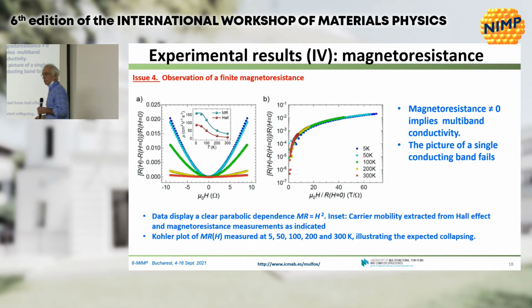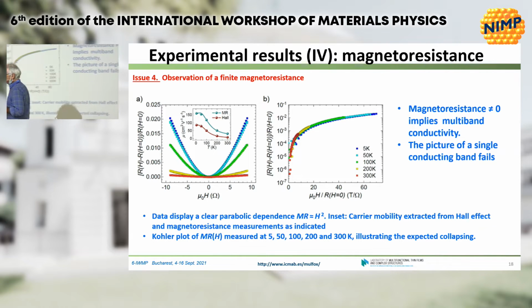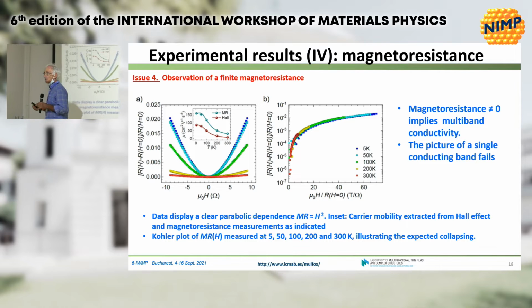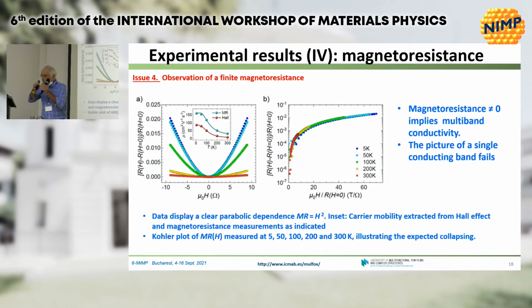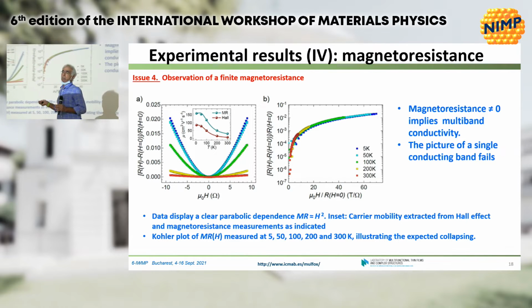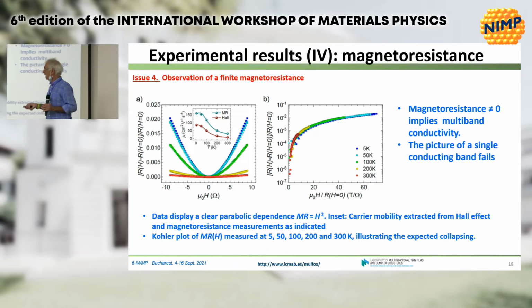There is another issue. In a normal metal, you take a metal with one electron in the conduction band. That is going to be, in the simplest case of a Sommerfeld material, even if you put correlations in there, the Fermi surface is going to be a sphere. And in a cubic material like this one, if the Fermi surface is a sphere, the magnetoresistance should be 0. But there is a clear magnetoresistance, a standard one, I would say almost B square dependence.